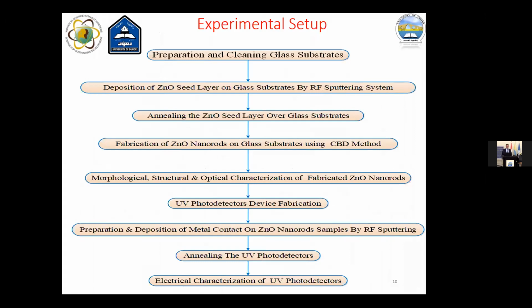The experimental setup of this research is: first, preparation and cleaning of the glass substrate; deposition of a seed layer on the glass substrate by RF sputtering using a high purity zinc oxide target; annealing the zinc oxide seed layer over the glass substrate at 400 degrees for 2 hours; fabrication of zinc oxide nanorods on a glass substrate using the modified CBD method; morphological characterization of the fabricated zinc oxide nanorods; UV photodetector device fabrication, and preparation and deposition of a metal contact on top of the zinc oxide nanorods by RF sputtering; annealing the UV photodetector; and the electrical characterization of the UV photodetector.